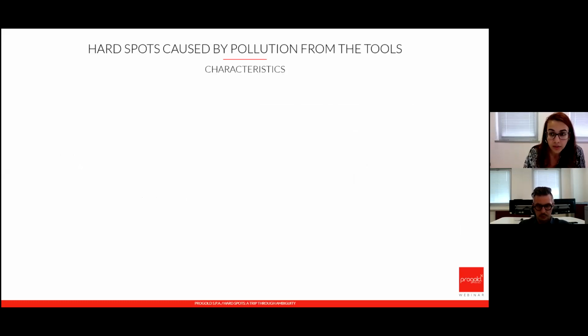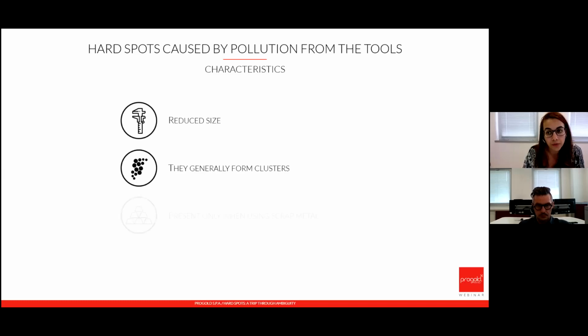Another case of contamination that we can have is from the use of tools. Differently from the first case, where we could have the issue also when we were using fresh metal, in this case we can only have the problem when we're using scraps, because the scraps are the ones that are in contact with the tools. They tend to have a very reduced size and they tend to form clusters.